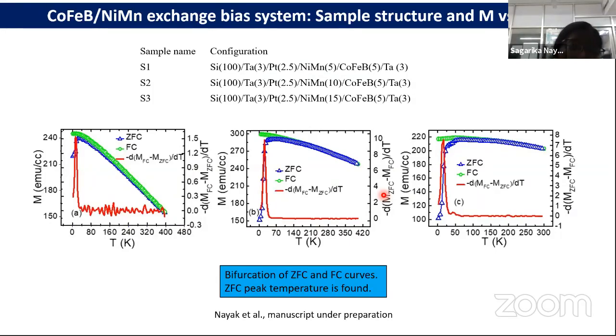We performed MT loop measurements on the system and found there is a bifurcation of the zero field cool curves at the lower temperature side, and there is a zero field cool maximum on this lower temperature side in all the samples. We found that this peak is broadened with the increase in thickness of nickel manganese, indicating that there is an increase in interaction with the increase in thickness of the nickel manganese.